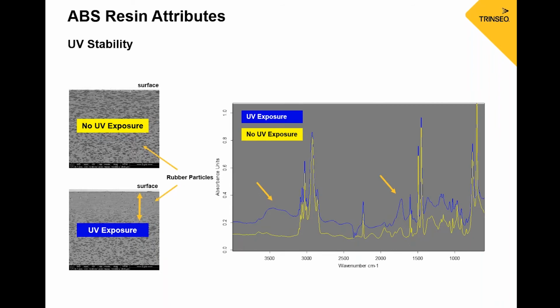So here, this is not directly related to the comparative study, but is more an ABS resin attribute of what you could look at if you are experiencing part failure, something you can look at to see if it's related to the UV energy absorption. On the left, I'm focusing on the rubber aspect, and on the right, the FTIR spectrum focusing on the SAN component. There are two modes where you could see degradation due to UV energy exposure. And those TEM images that I was talking about earlier are what we're seeing here on the left with the rubber. On the top, there's no UV exposure.